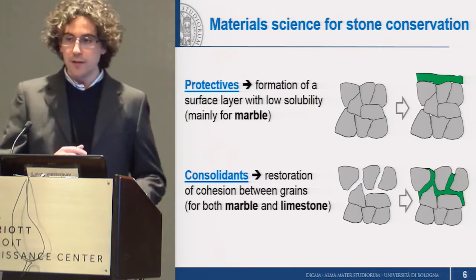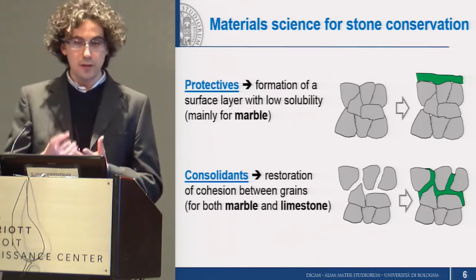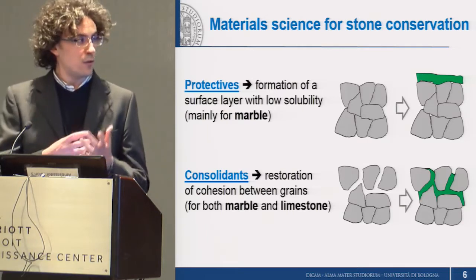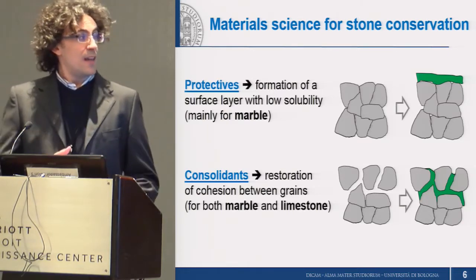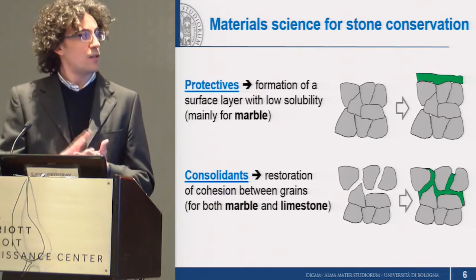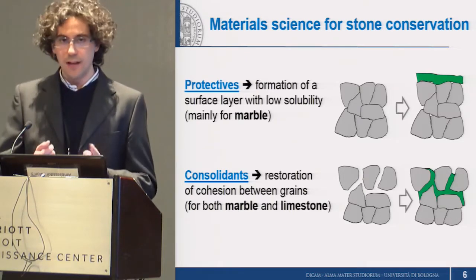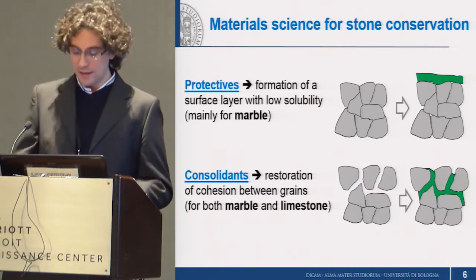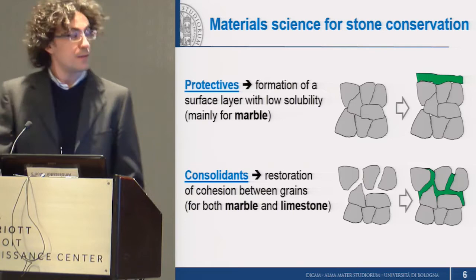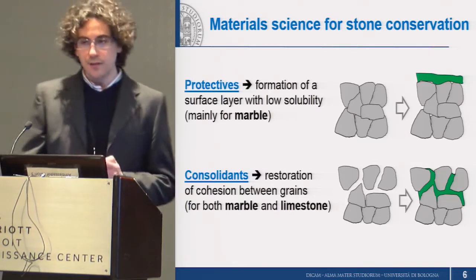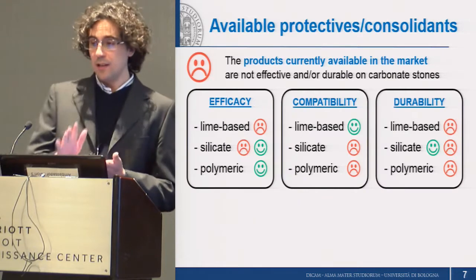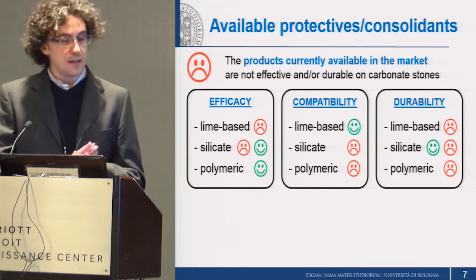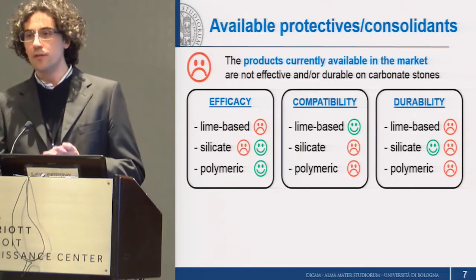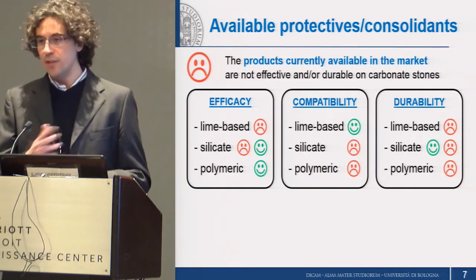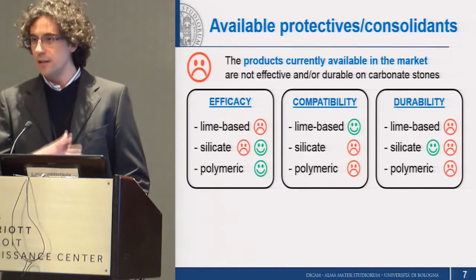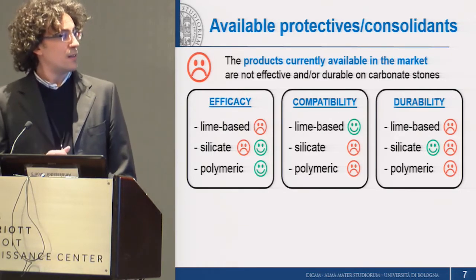While consolidants are products that are aimed at penetrating into the stone, into the pores in the case of limestone, for instance, or in the microcracks that develop in marble, and then reacting with the substrate to bond the grains, so as to reestablish cohesion between grains and increase mechanical properties. Unfortunately, at the moment, all the products that are available in the market, which are basically silicate consolidants, lime-based consolidants, and polymeric consolidants, all have limitations when applied to carbonate stones in terms of either efficacy, compatibility, or durability, that are the main requirements that these products must meet.